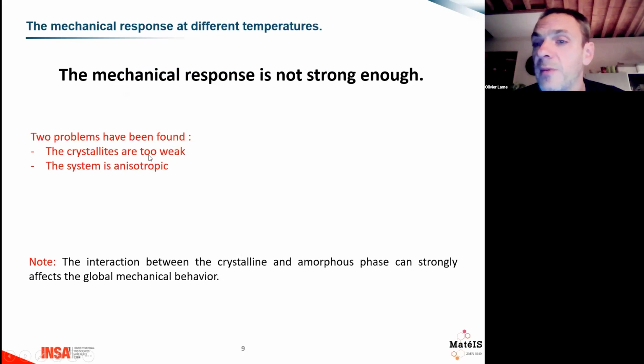The first problem is that the crystallites are very weak, and it is very easy for the chain to be pulled out from the crystal, which is not realistic for the real system. But our model is too simple, and it's impossible to prevent the chain from being pulled out from a crystal. So it means that the crystallites are very weak. Also, the system is anisotropic, and when we stretch it, it is difficult to compare the different systems because the different crystallites didn't grow in the same direction, and there are too few to be averaged. So it is difficult to compare.